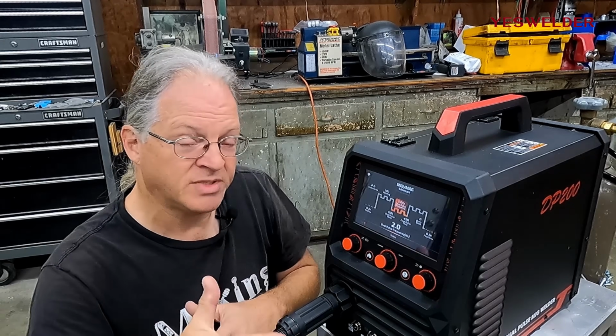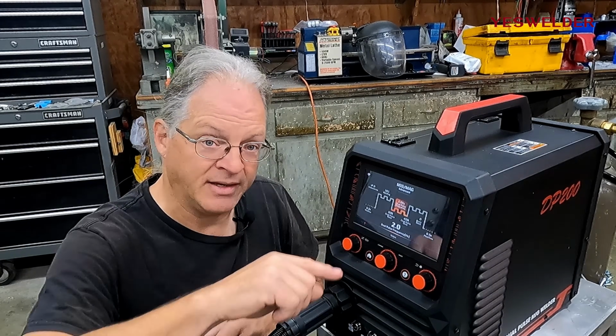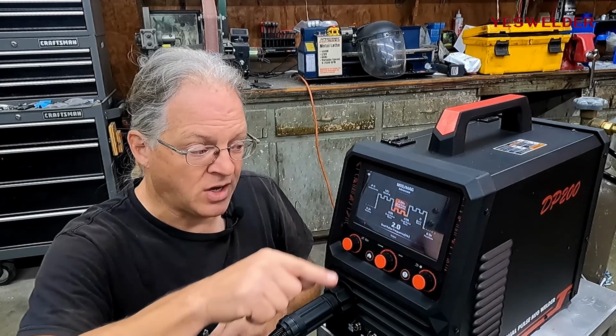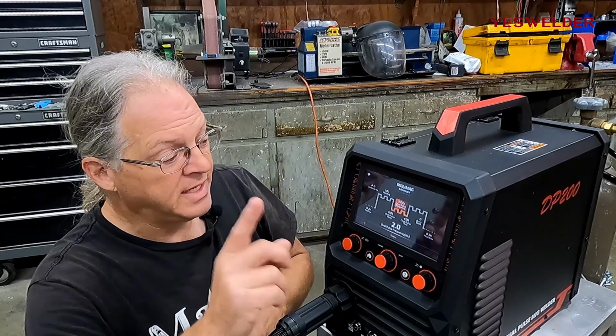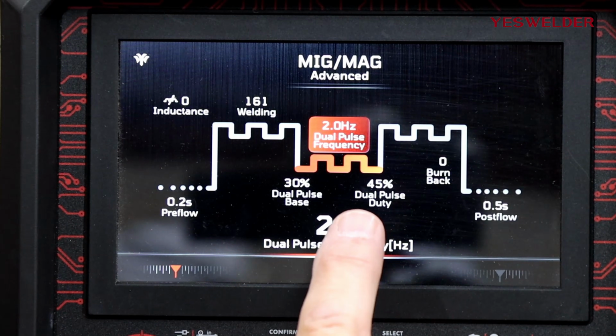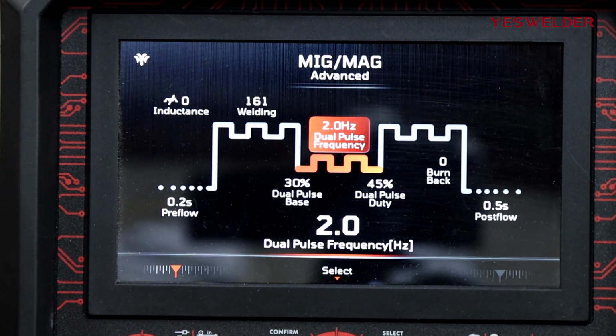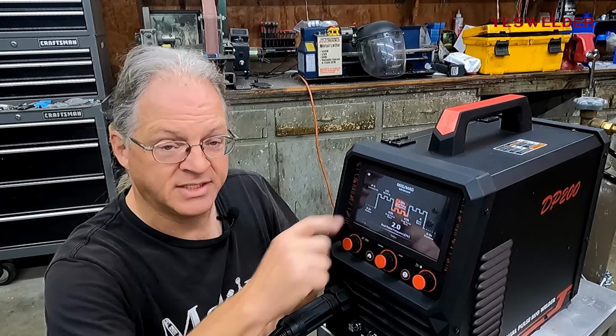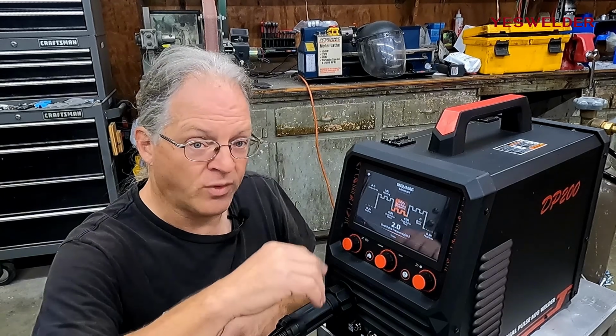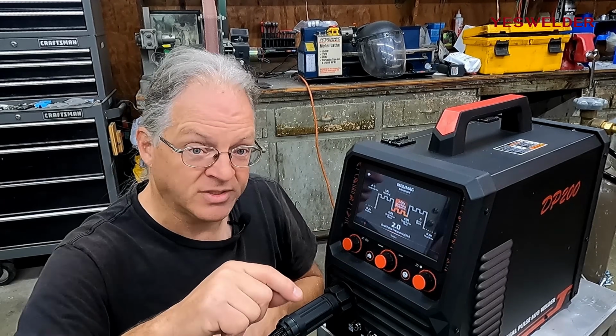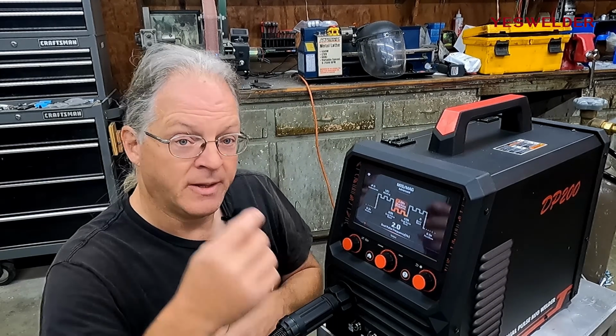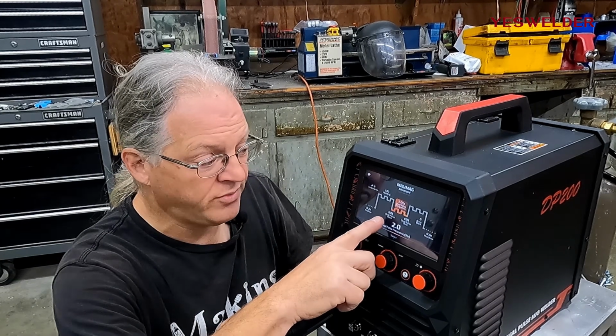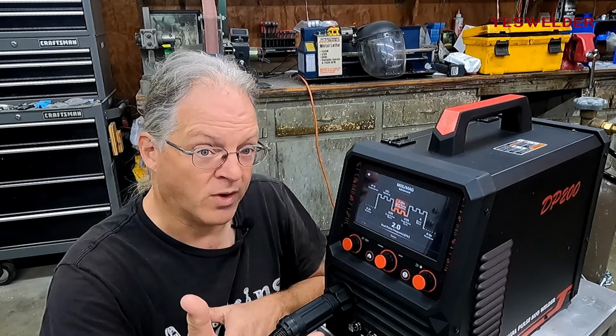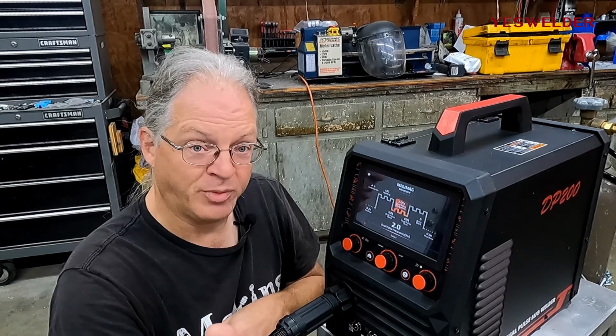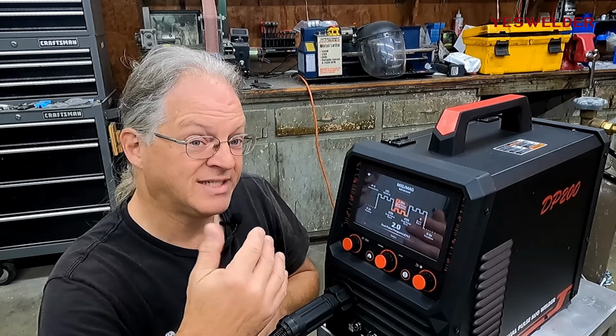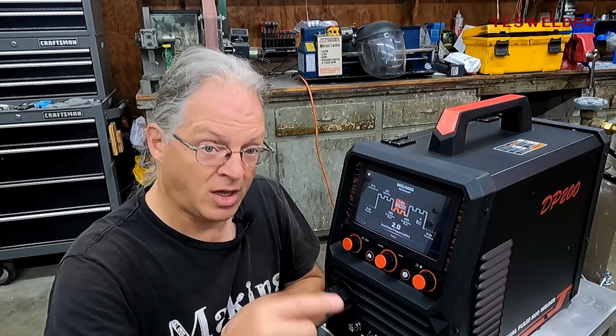So that roughly comes to 24 amps. That means when that double pulse is down at its lowest setting, it is only set to 24 amps. Now, I also dialed back the duty cycle to 45%. That means that maximum 80 amps, 161 inches per minute is only on 45% of one of those double pulse loops. The other 55%, the double pulse is set to that 30% setting, which is 24 amps. So that means that 45% of the time I'm at the max setting and the other 55% of the time I'm at the lower setting.